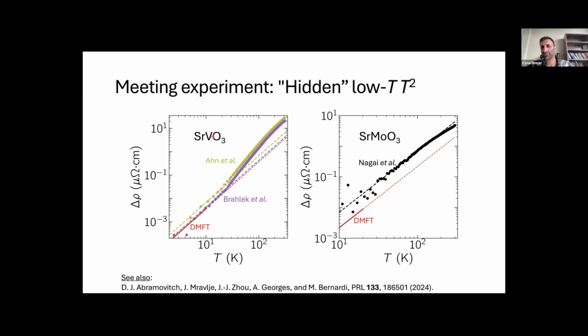In strontium vanadate, the electron-phonon scattering is a lot stronger, and enhanced by correlations, and therefore it's a cleaner distinction between the two. Whereas strontium molybdate has such superlatively low resistivity because the electron-phonon scattering is so low, and so the offset between DMFT and what we predict for the electron-phonon is somewhat less. Okay, great. Thank you. So I guess the real answer to my question is that for this material the issues are still open.